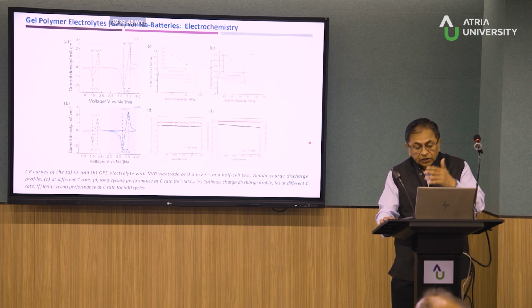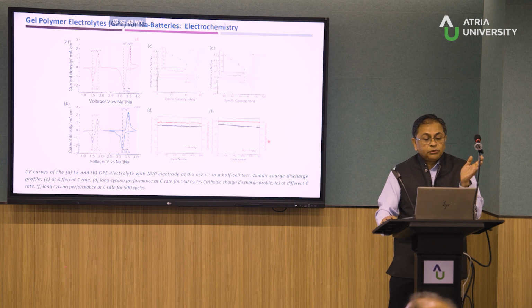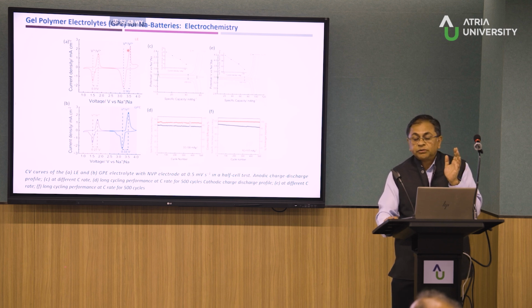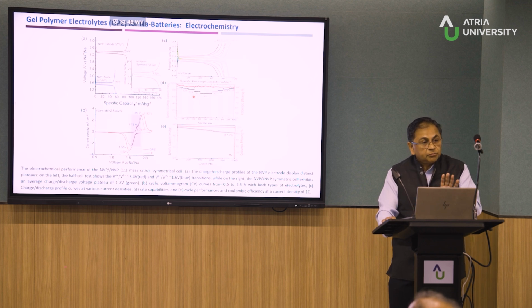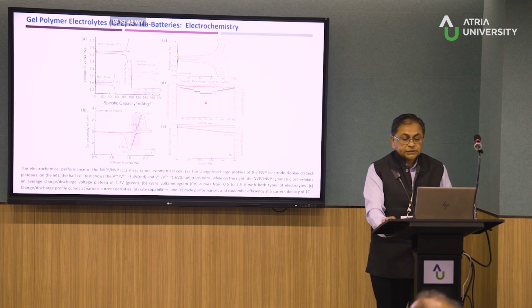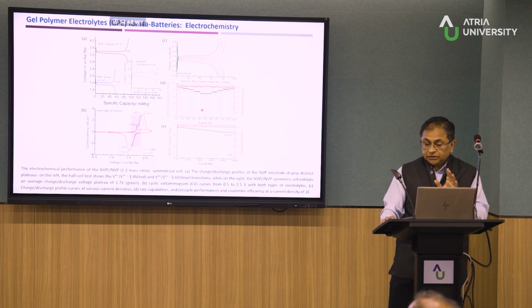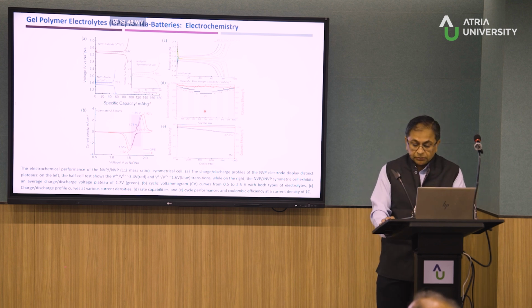You can run for 500 cycles. It's very interesting. This polymer is stable in both zones of the voltage window. So you can make the polymer work with the V3, the vanadium 3+/2+ redox couple. You can also make it work with the 4+/3+ redox. So these are half cells. You can actually also make the full cells, and you can have a pretty good battery running for 1,000 cycles. So these are pouch cell data, which I'm actually showing here.